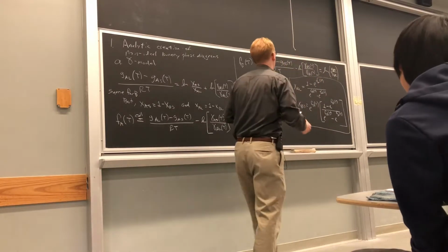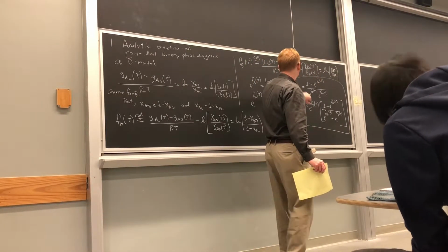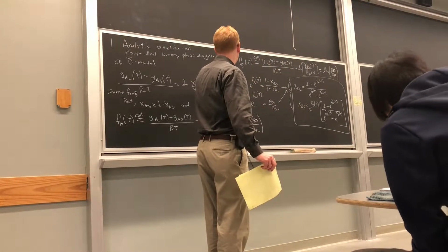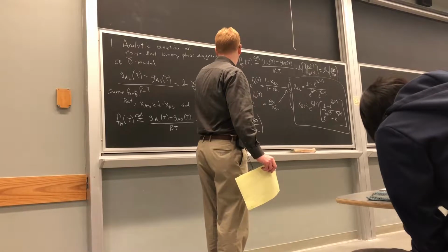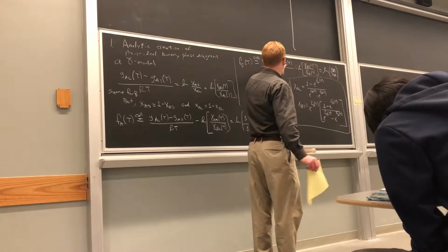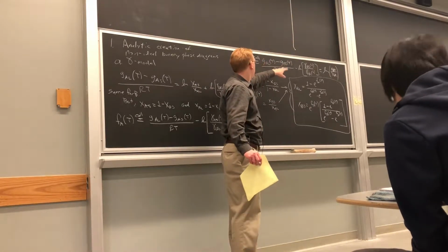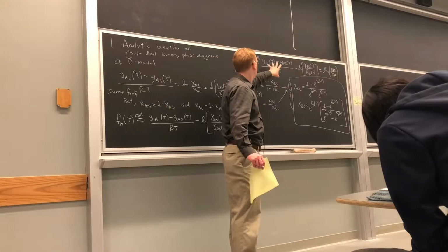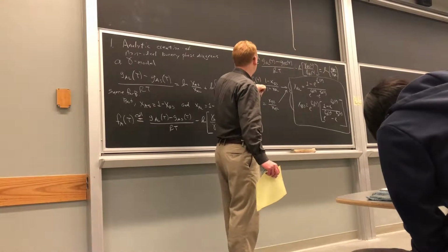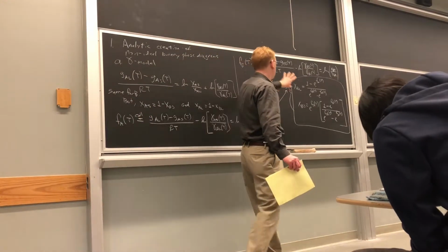So what do we have here? Again, this is now for non-ideal solutions, where we have the gamma in here. We didn't set those equal to 1, and so this term did not drop out. But basically, we just lumped it in with the other functions of T, the Gibbs free energies here, and the RT factor. We lumped that all together and just called it F_B instead of beta, and F_A instead of alpha, and got something that's somewhat of a similar form.